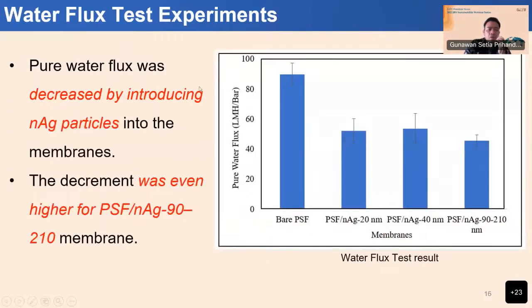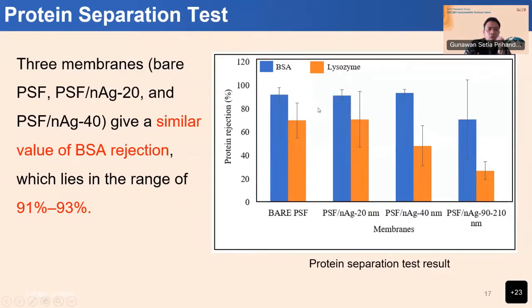Okay, based on the water flux test using pure water, we can see that the permeability of the membrane slightly decreased with the introduction of the nanosilver powder, and got even worse with the bigger nanoparticles. It's understandable that the silver powder blocks the pores of the membrane surface. And then for the protein adsorption, we can see here that